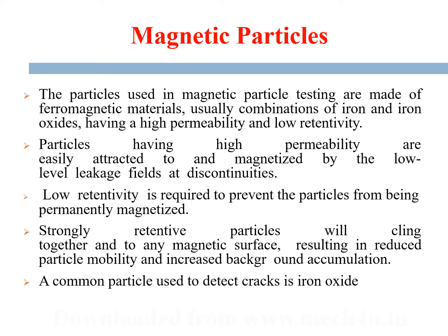Now, strong retentivity particles, as discussed, will cling together to any magnetic surface, resulting in reduced particle mobility. That is also a reason. That is, the removal will also be difficult, as well as the fact that if you are using high retentivity particles, then they'll form clusters at each and every location. So it is difficult to interpret the results. That is, we cannot easily find out where the defects are occurring. So we need to go for particles having lower retentivity.